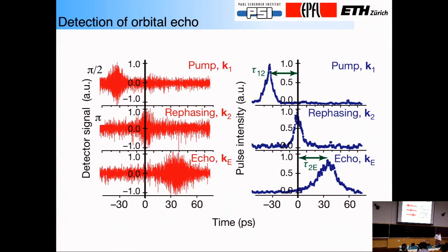I can rectify that and look at the amplitudes, and now I get something which looks very much like electron paramagnetic resonance. But what's really remarkable here is that I have now seen in a solid, for the first time, an orbital echo coming from a superposition of two wave functions, both of which are very, very large. So this is now looking at these electronic states. The fact that I can see an echo at all means that they're coherent on time scales of 100 picoseconds or so, over a spatial extent which contains of order 1 million silicon atoms. So that tells you how clean the silicon is. That's a remarkable fact of life.